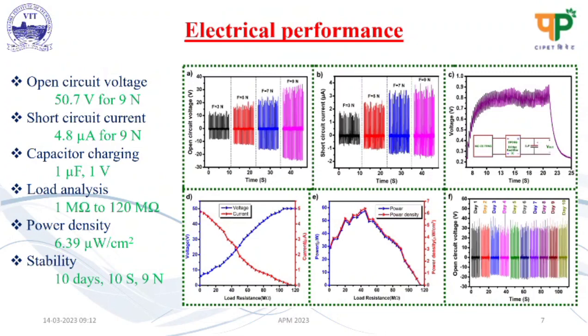The device was connected to a bridge rectifier and a capacitor to test its capacitor charging performance, and it could charge up to 1 volt within 10 seconds. Output voltages and currents were measured for different load resistances ranging from 1 mega ohm to 120 mega ohm, and then multiplied the instantaneous values of voltage and current to obtain the instantaneous value of power and the power density. For this device, it obtained a maximum power of 57.5 microwatt and a power density of 6.39 microwatt per centimeter square at 45 mega ohm load resistance.